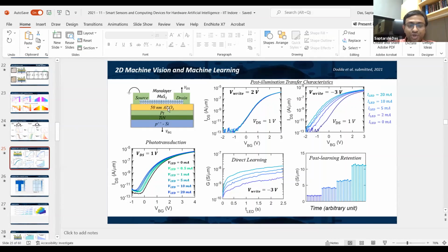When I illuminate in the off state, although the electrons can get released, because these are Schottky barrier devices, my holes cannot really get released. They have a much higher chance of getting captured by the alumina, and that results in a threshold shift. So depending upon the condition in which you are illuminating, you will either have persistent photoconductivity or not. Here the device works like a normal photo sensor, with response up and response down. That is what you need for stochastic resonance. If I try to use persistent photoconductivity for stochastic resonance, it will not work.